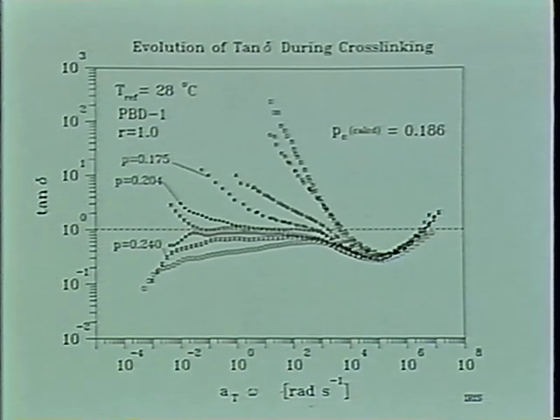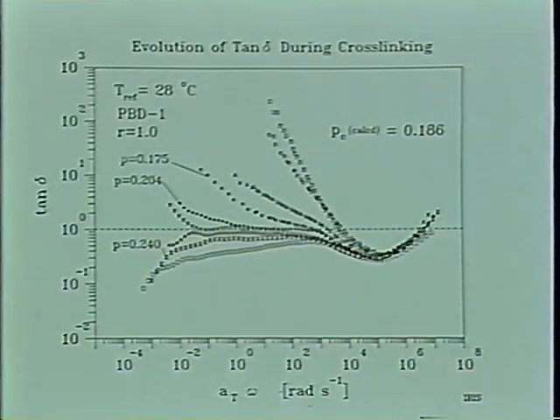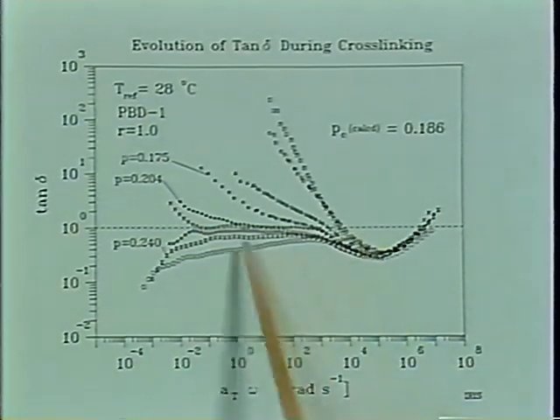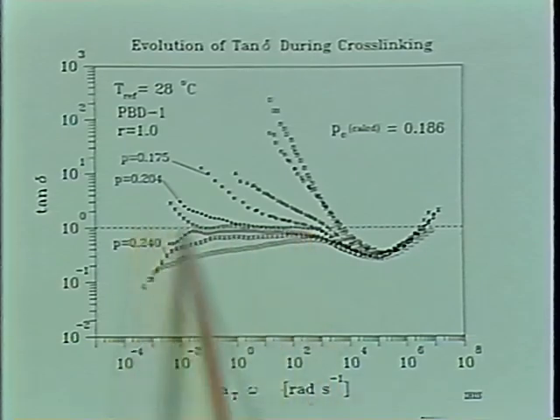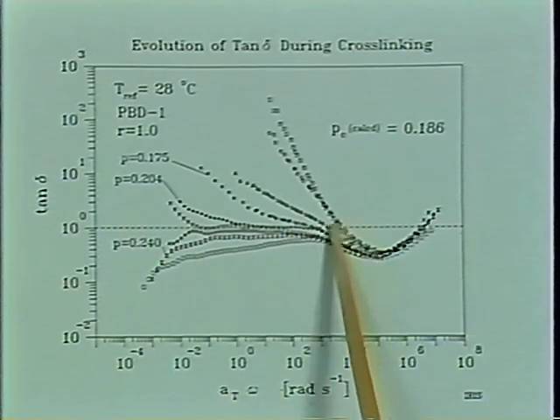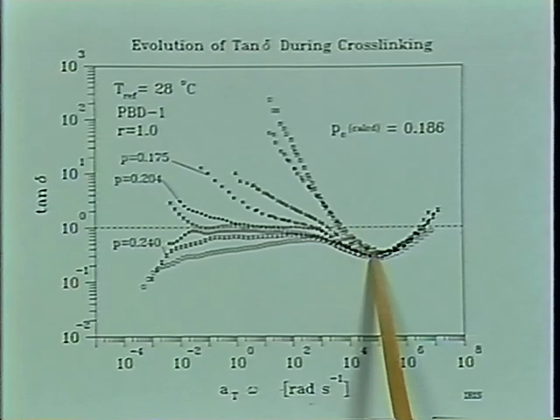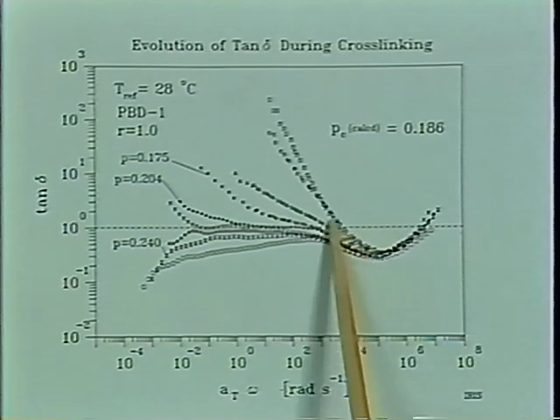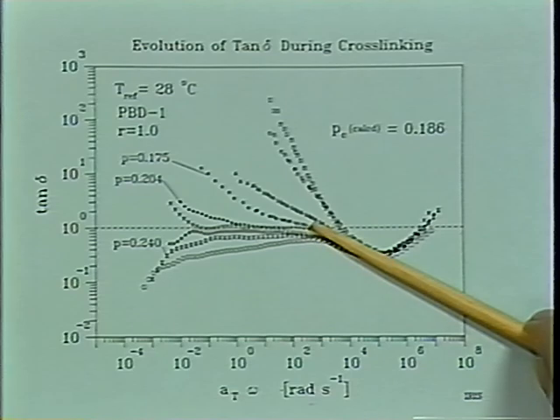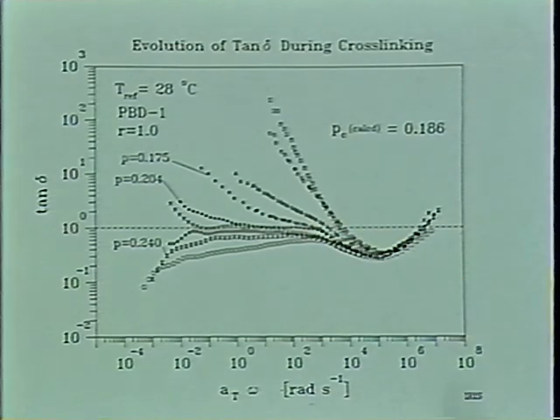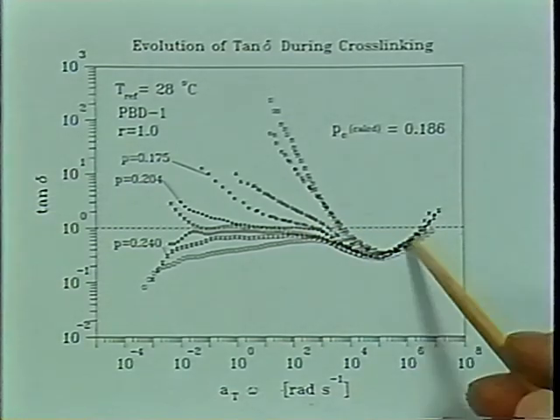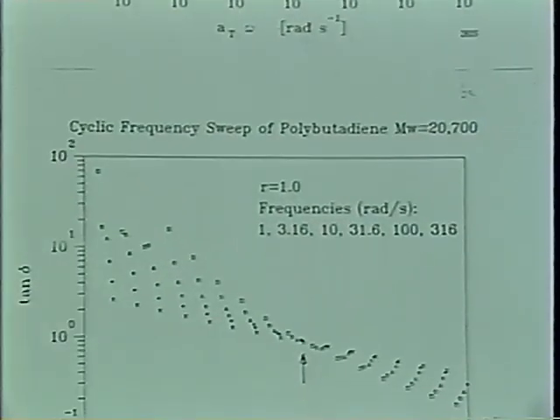Theory of Flory and Stockmayer predicts about 20% conversion if you crosslink a system which has a functionality of 6. Okay, so that's pretty consistent. And again, you see the terminal zone adopting this power law behavior. This region is known from the entanglement behavior. See, it goes down with a slope of minus n about, and this is the transition to the glass at very high frequencies.